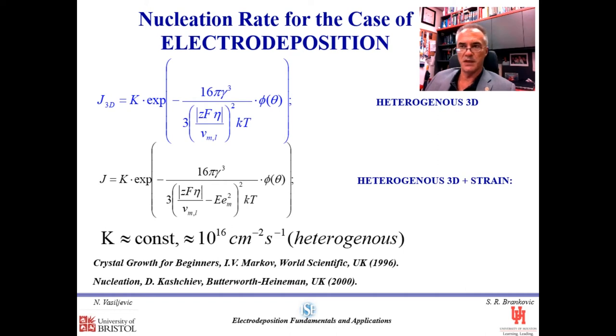When we talk about thermodynamics of nucleation, we're talking about nucleation rate. Nucleation rate is a function of the overpotential, and it's an exponential function where the overpotential is squared within the exponent, with one over the overpotential squared. And one important thing to appreciate is that if we have a substrate for our electrodeposit which has a good epitaxial match, let's say we just do homoepitaxial deposition like silver on silver, silver on gold, where the small misfit doesn't create a lot of strain, then we can use this relation.